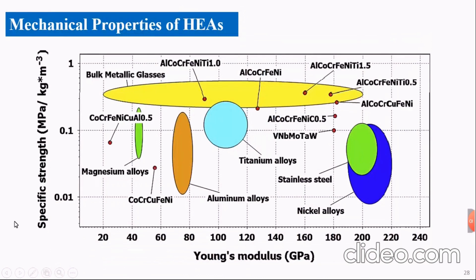When we come to the mechanical properties, if we compare the specific strengths to Young's modulus for different alloys, we can find that high entropy alloys have the highest specific strengths compared to the other alloys, even compared to the titanium alloys and superalloys, which is very interesting. And the good thing is that we have this high specific strength over a wide range of Young's modulus. So you can choose the Young's modulus you need according to your application, and you will still keep the high specific strengths.